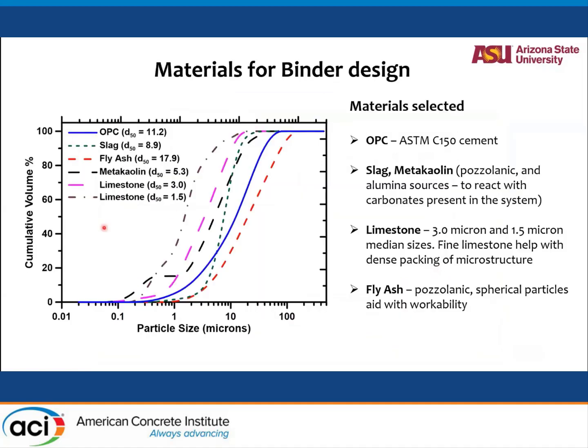So here are the particles. We used ordinary Portland cement, we've used slag, we've used fly ash, metakaolin, limestone of different particle sizes. Not all of them in the same mix, and I'll explain that as we go through, but combinations of these different materials based on certain criteria.